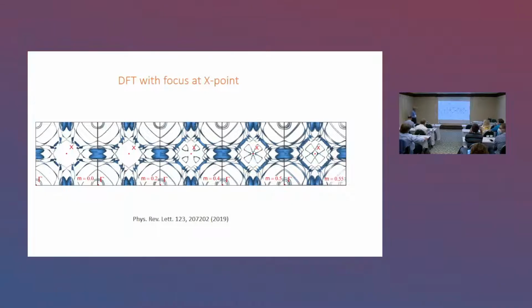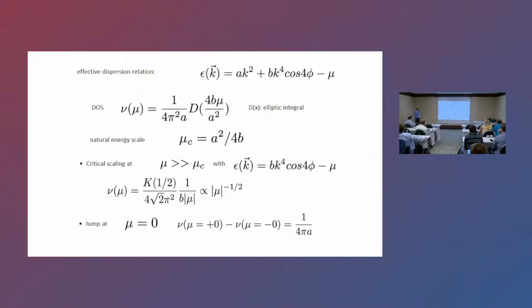And then if we focus at the X point, so basically at the corner of the Brillouin zone, you see magnetization 0, nothing happens. 0.2, nothing happens. 0.4, 4 pockets appear. And 0.5, they merge here into a topological transition. And then a little bit above, you see that this topological transition is destroyed.